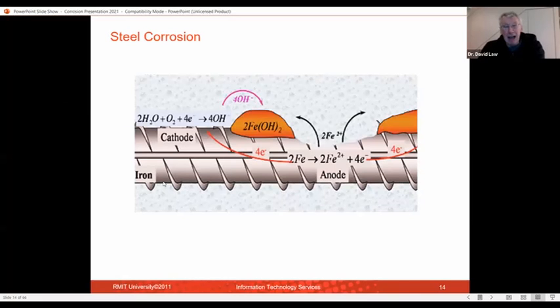And this is what happens. You set up an electrochemical cell. You have an anode, and that's where your iron dissolves from your steel. So your Fe goes to your Fe2+, and you have 4 electrons generated. And these move along the rebar to an area on the bar that we would term the cathode.